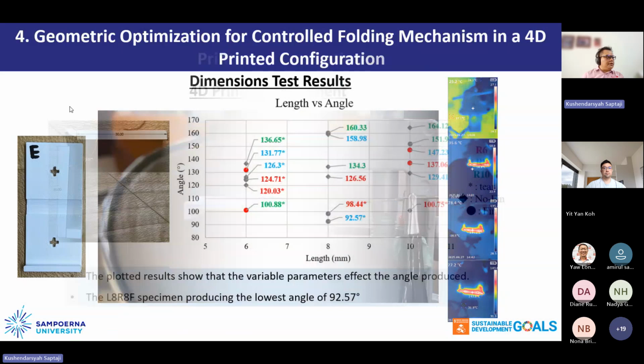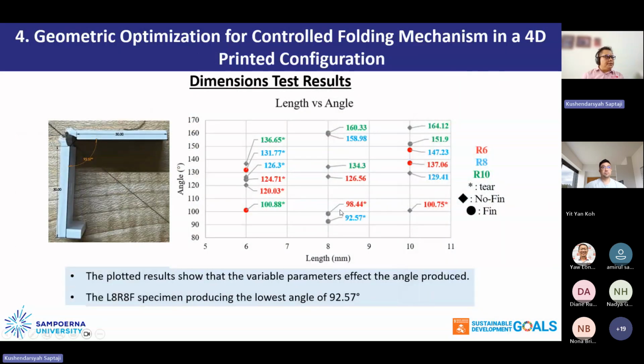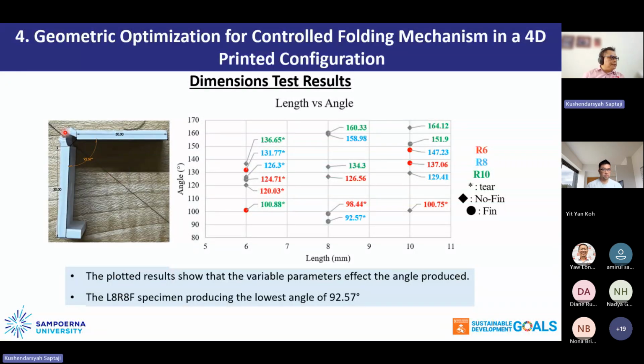From there, we measure the angle of deflection for different parameters. Some of the specimens were torn, as you can see in this slide; there is some tearing of the bending area. Some specimens, maybe because they were too thin, tore and got damaged. But some show good results. We can conclude that with length 8 millimeter and radius 8 millimeter with fin, it produced the lowest angle, which is about 92 degrees.